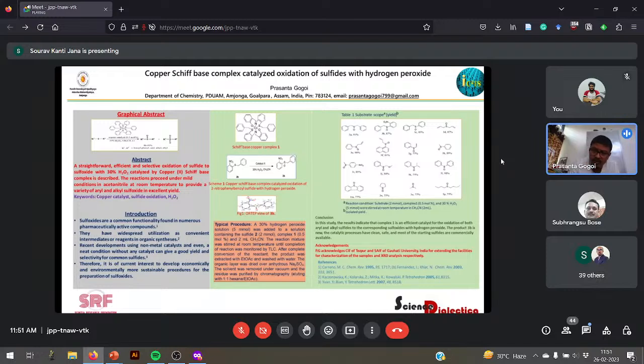In the most typical procedure, we use a 30% hydrogen peroxide solution, here 5 millimole, added to a solution containing the sulfide, the copper Schiff-base complex and 2 ml acetonitrile. The reaction mixture was stirred at room temperature, and completion of the reaction was monitored by TLC. After complete conversion of the reactant, the product was extracted with ethyl acetate and washed with water. The organic layer was dried over anhydrous sodium sulfate, the solvent was removed under vacuum, and the residue was purified by chromatography.